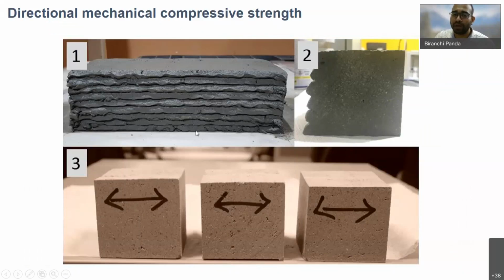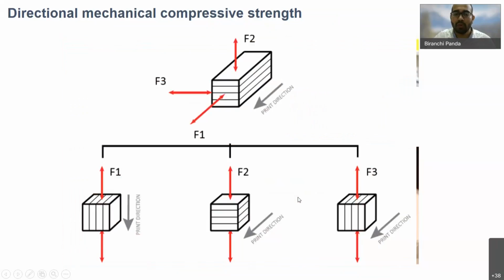To prove that, we printed a block and then extracted these blocks out of this big cube. Okay, and then we applied force in different directions, F1, F2, F3. You can see these layers are oriented in different directions. We applied force in different directions and we wanted to see whether this concrete is going to have the same property in all directions or a different property.